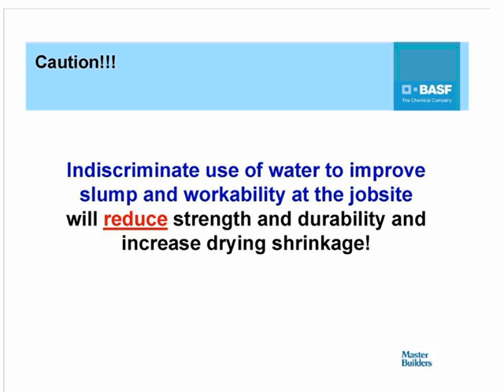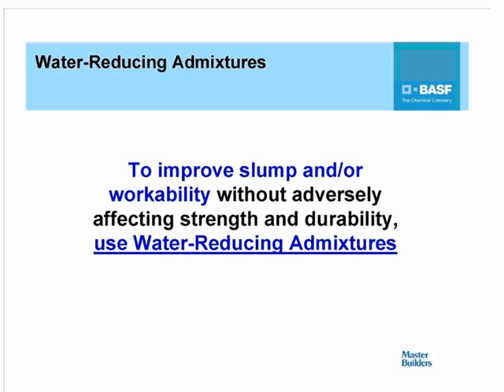And at this point, what I'd like to bring up is this caution, and that is that the indiscriminate use of water at the job site to improve slump and workability will invariably reduce the strength and durability of the concrete, as well as increasing the drying shrinkage of the concrete. So as much as possible, the best thing is to keep the water content as needed and have ways in which we can improve the slump or workability of the concrete.